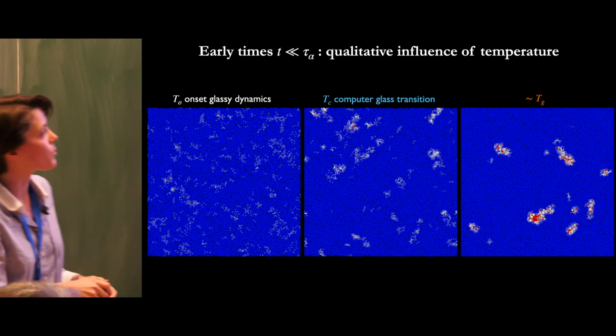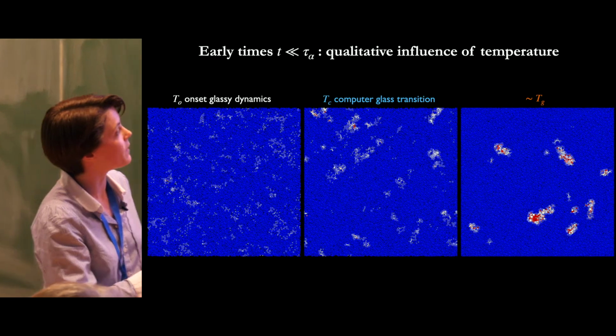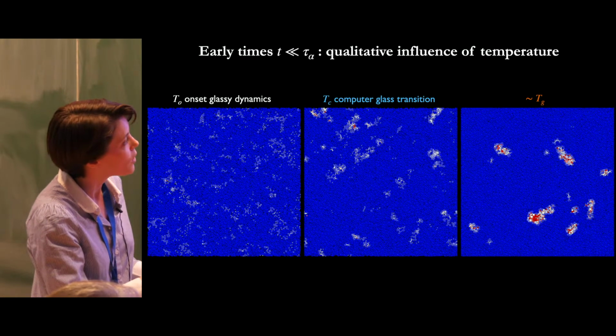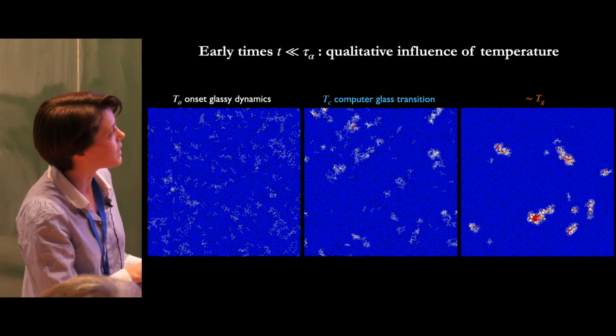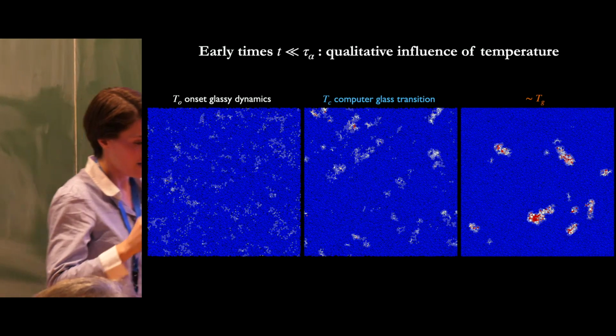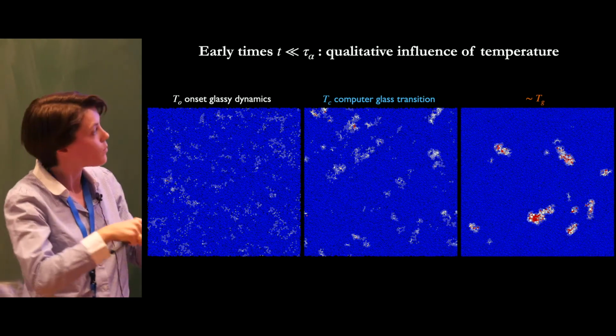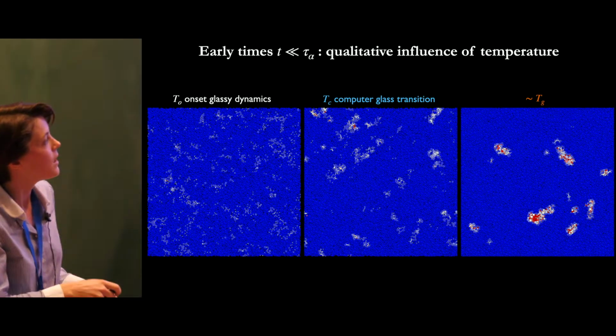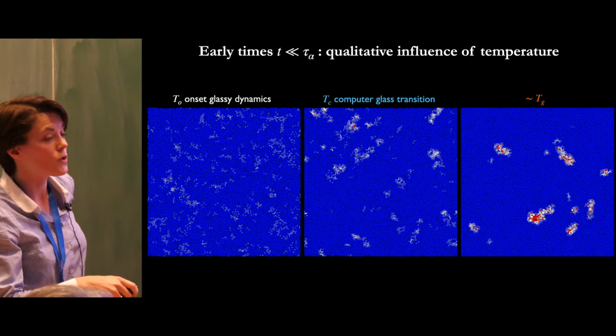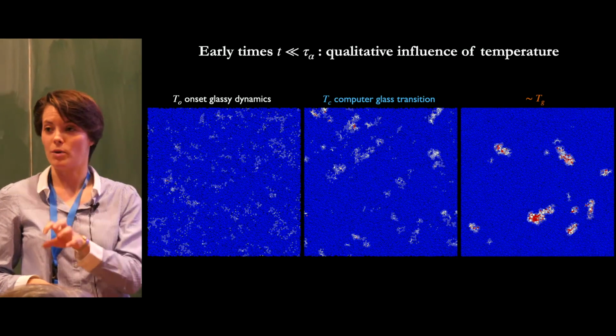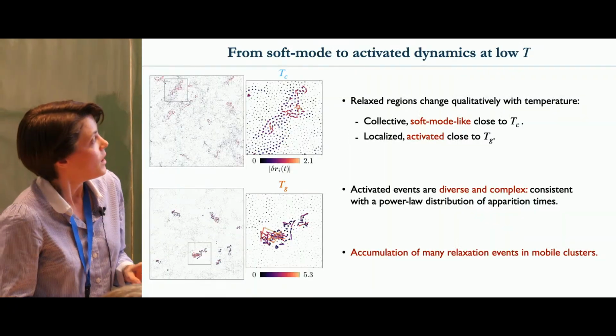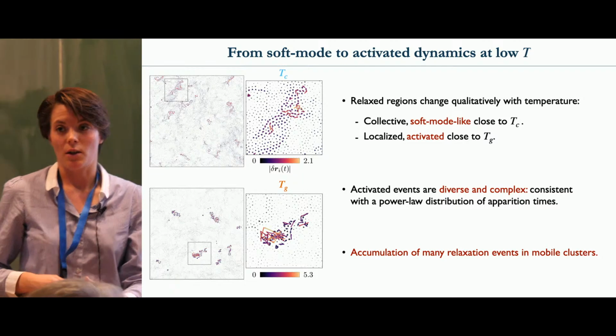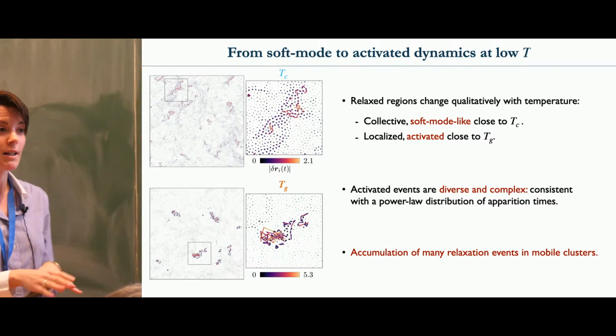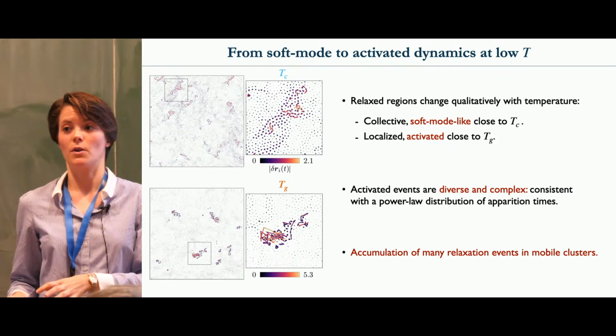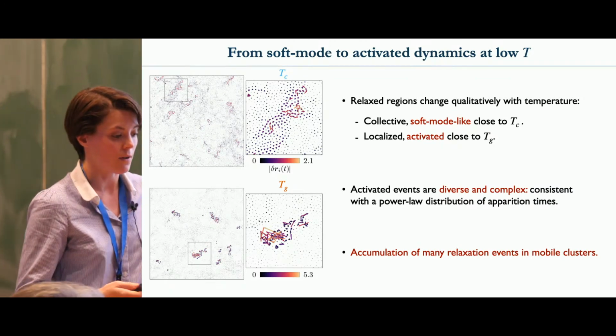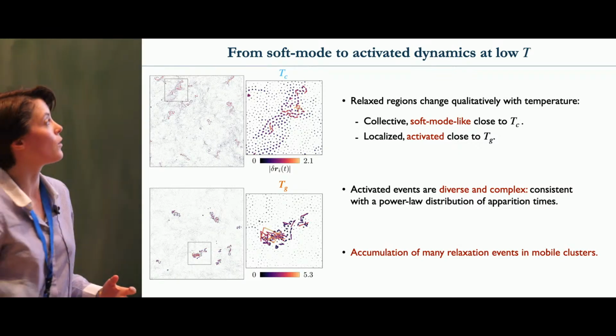Close to the mode coupling crossover, you have a picture that's maybe a bit clearer, where you start to have some more compact zones, but still in these regions it's a quite subtle move. I will show you in the next slide. And you really need to go to extremely low temperatures to see these well compact regions start to appear. So going a bit into these discussions that we've been having about collective moves corresponding to soft modes versus activation events, that's a long-standing debate in the community.